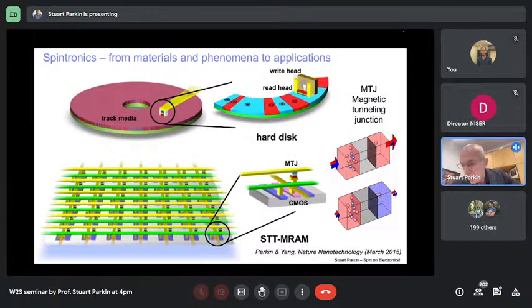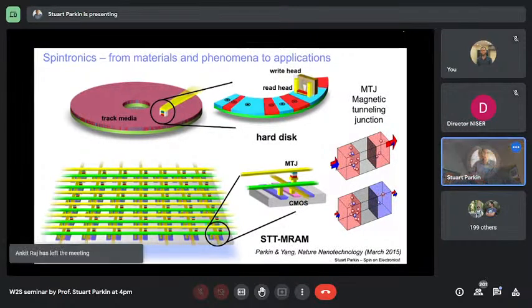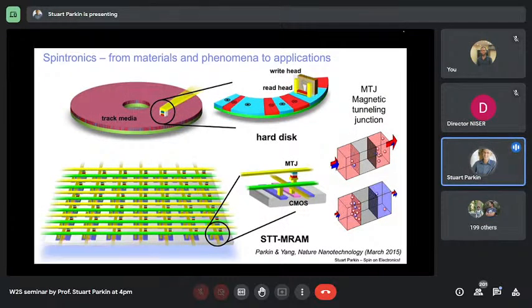And we can basically change the resistance of the device so that it is optimally designed to be compatible with the input resistance of a transistor, an FET. And the transistor then is used to pass current through the device and to detect how much that current is. When the two magnetic moments are parallel to one another, as in the top, the current flows very easily. You get a big current. And when the moments are anti-parallel, then the resistance is much higher and the current is reduced.